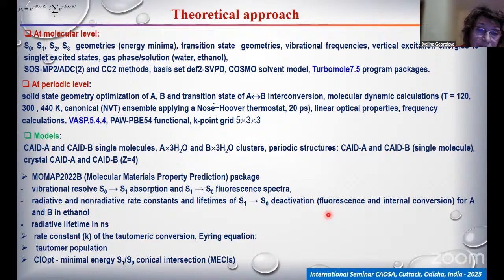Different approaches are also applied to calculate vibrationally resolved absorption and emission fluorescence spectra, where the vibronic corrections are taken into account in this simulation. We calculated radiative and non-radiative rate constants and lifetime of deactivation processes in solution. Also, the rate constant of tautomeric conversion using corresponding formulas.